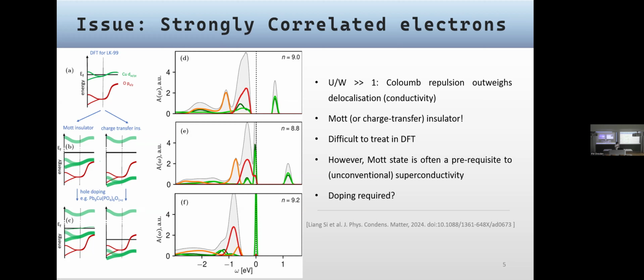So the strongly correlated nature of, in this case, the copper 3d orbitals led to the Coulomb force overcoming the gain in energy from the conductance, and therefore the material became insulating. This figure that I showed proves it with the DMFT, but they also showed that in the case of this model system, by introducing doping, this Mott gap can be closed, and we can bring back the conductivity as well. This kind of behavior, being a Mott insulator and then becoming a metal via doping in some range, is also reminiscent of the high temperature superconductors.